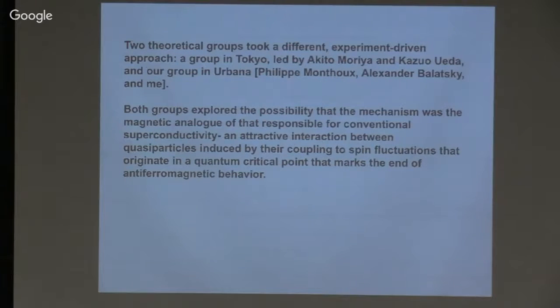And two groups took a different point of view. A group in Urbana and a group in Tokyo, led by Moriya and Ueda. What we looked at was the possibility that we were seeing the magnetic analog of the phonon-induced attraction between quasi-particles. But what is providing the glue then are quantum critical fluctuations induced by the fact that all of these materials are near a quantum critical point. The end of antiferromagnet, they all are antiferromagnets at some doping or pressure. And that end point then gives rise to quantum critical fluctuations that you can describe very nicely.